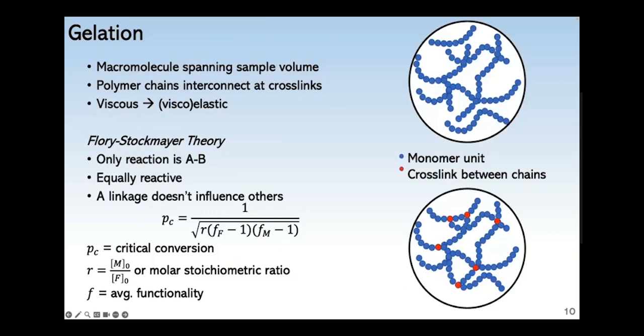So gelation criteria were really important for my analysis. So I'll make a few comments on this slide. It's the process where a single molecule comes to span the entire sample volume. And that's possible if one of the reagents has an average functionality greater than 2, so that enough chains become interconnected and form a 3D network. And this will change the resin from just viscous or liquid-like character to a material with viscoelastic or solid and liquid character. One of the major statistical arguments that describe the process is Flory-Stockmayer theory, which has the general assumptions listed here. The first one is that reactions only occur between two types of functional groups, and two, one crosslink won't influence another crosslink's ability to form.